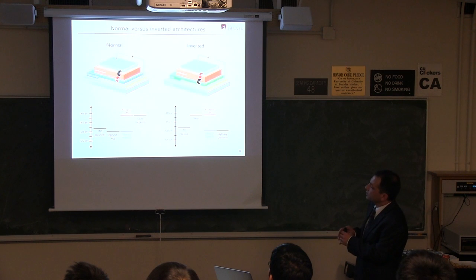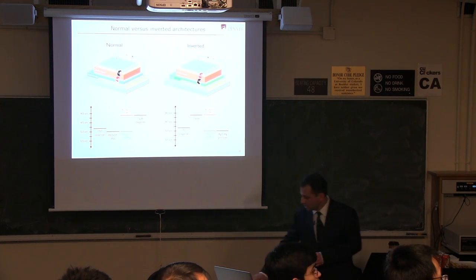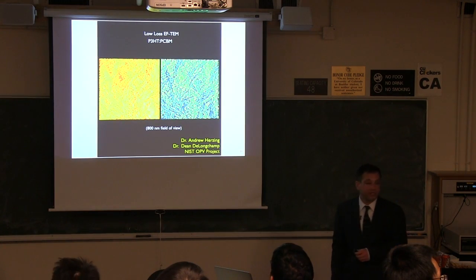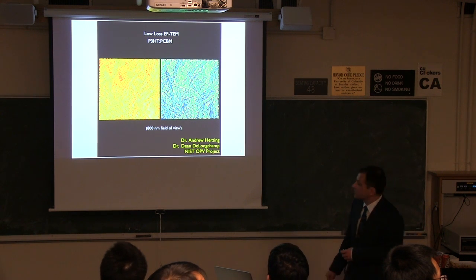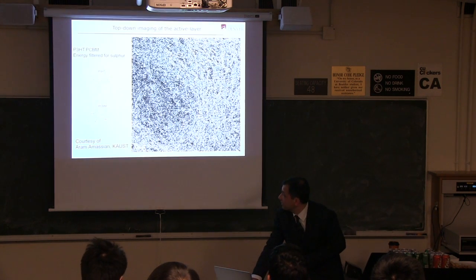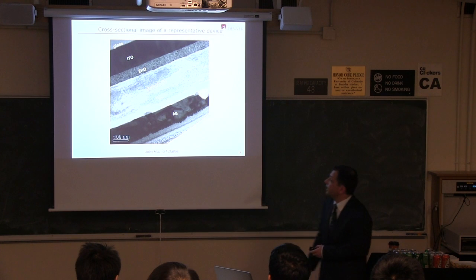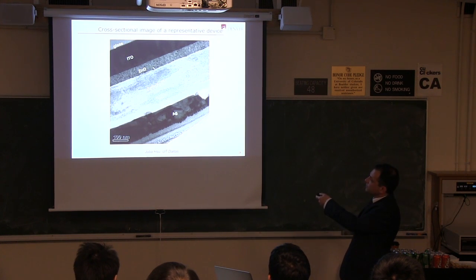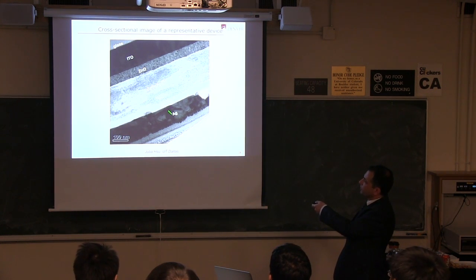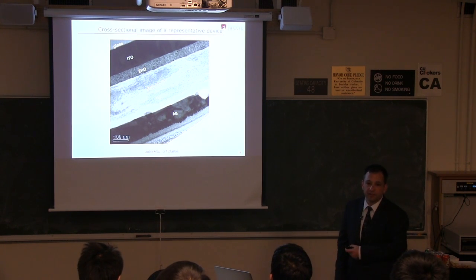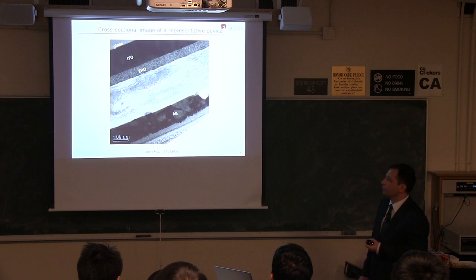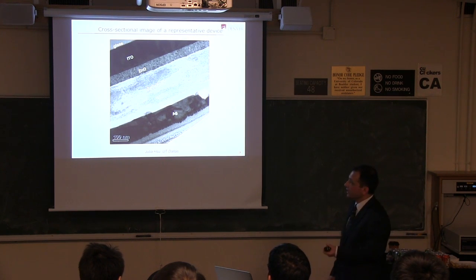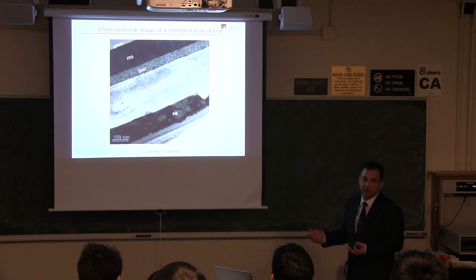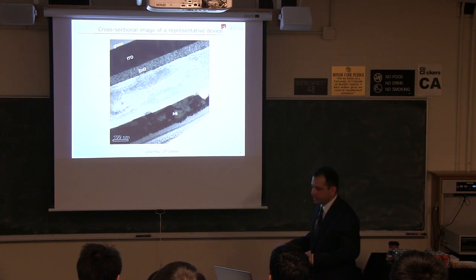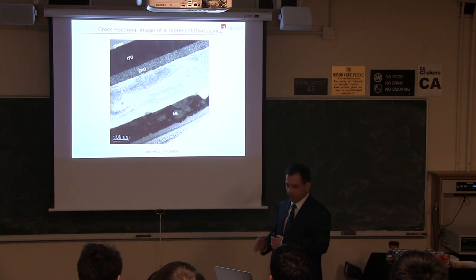Okay, just real quick. And this is a bulk material? This is a film that's 200 nanometers thick. So the active layer film, let's go back to the cross-sectional TEM. Thanks for reminding me. This is about 200 nanometers. This is about 100 nanometers. So the whole active layer of the device with ITO is about half a micron. These are truly thin film photovoltaics, right? So amorphous silicon is a couple microns thick, but these are much thinner. That's because of the large absorption cross-section of organic chromophores.